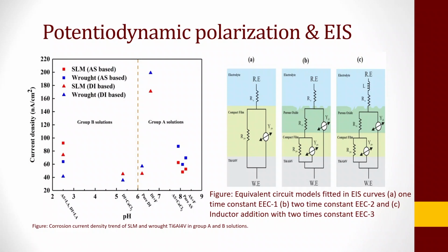These are the equivalent circuit models on the right, which we fitted using the EIS data, and we have drawn 3 different models to depict 3 different oxide film behaviors. And we have also run some other experiments, and we got the corrosion current densities, and the corrosion current densities of both samples are depicted in the diagram on the left.